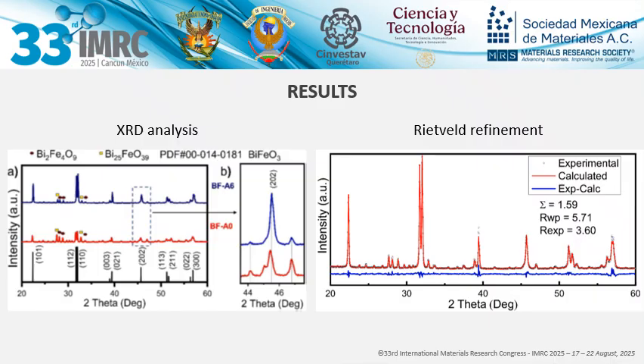Results. Structural analysis. Doping with 6% aluminum stabilized the hexagonal R3c phase and reduced the presence of secondary phases such as Bi2Fe4O9 and Bi25FeO39. Rietveld analysis revealed a distorted perovskite-type structure, with a slight contraction of the unit cell when aluminum 3+ replaced iron 3+, due to its smaller ionic radius.